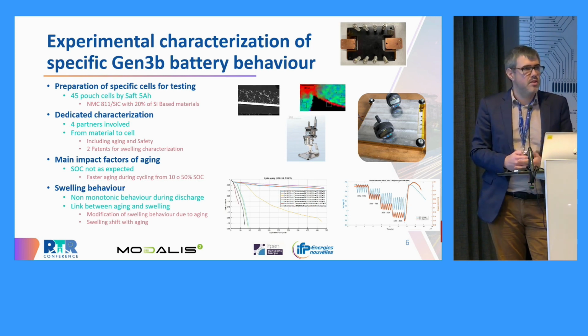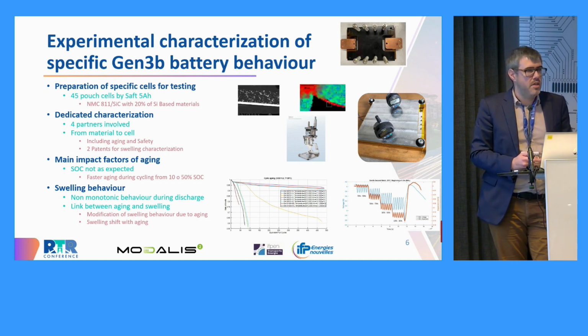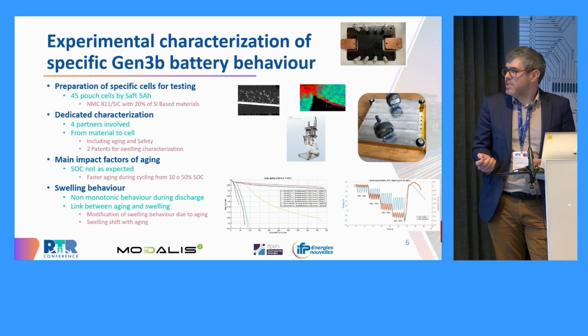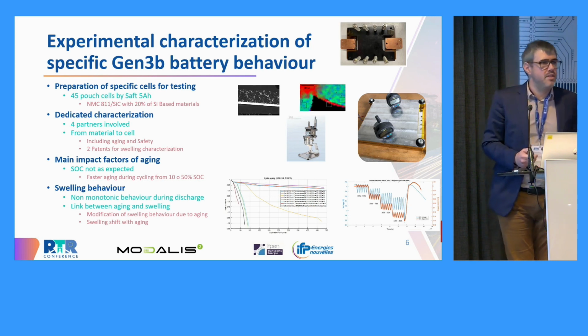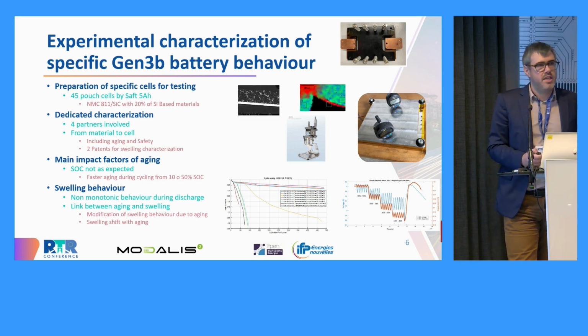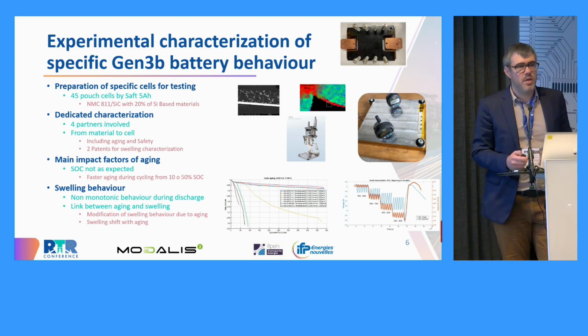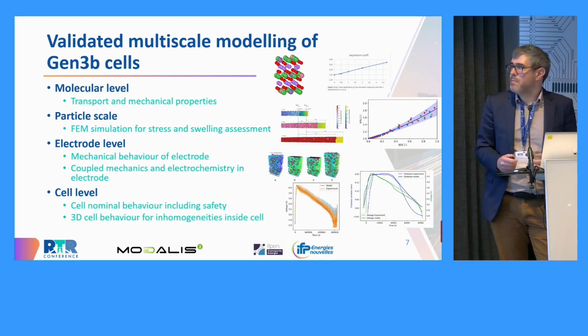And we saw that with some conditions, we had a very fast capacity degradation. Also, we were able to see some very specific behavior regarding the swelling due to the intercalation, the differentiated intercalation of graphite and silicon. So it was very interesting to see that and to see how the model compares to this kind of behavior, to see whether we were able to tackle this specific behavior.